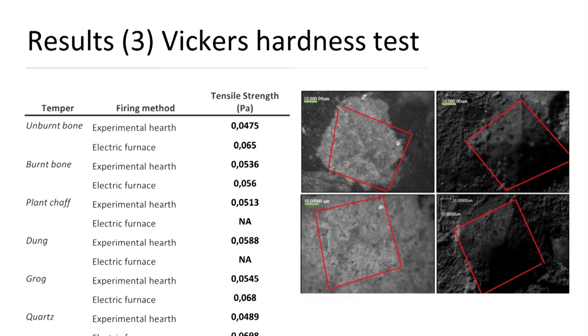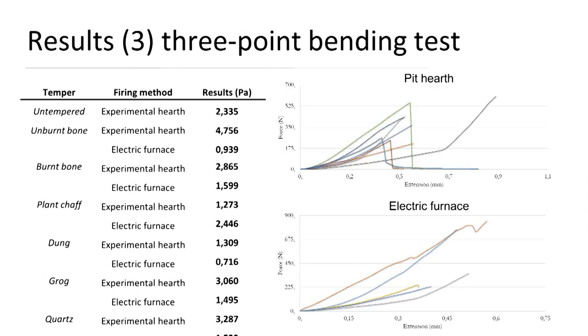Another takeaway of this test is that it's also not suitable to be applied to experimental specimens fired at low temperatures, such as 700 degrees, because as you can see, it was very challenging to measure the indentations, as the petrography is not extremely clearly defined. On the other hand, interesting results were obtained from the three-point bending test.